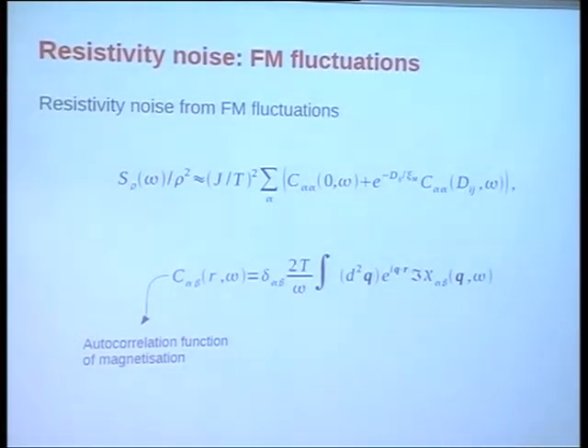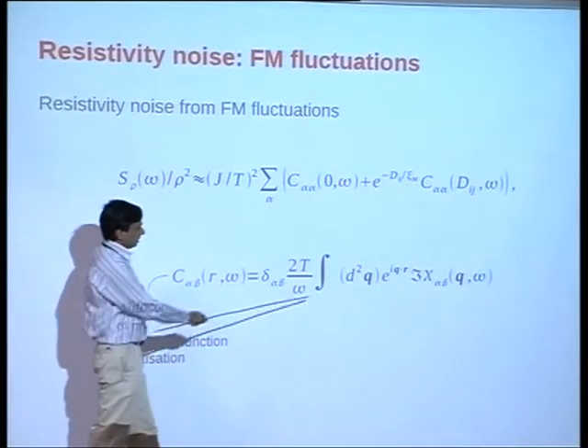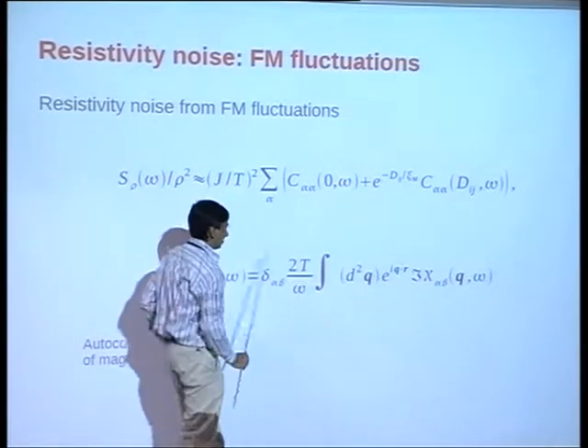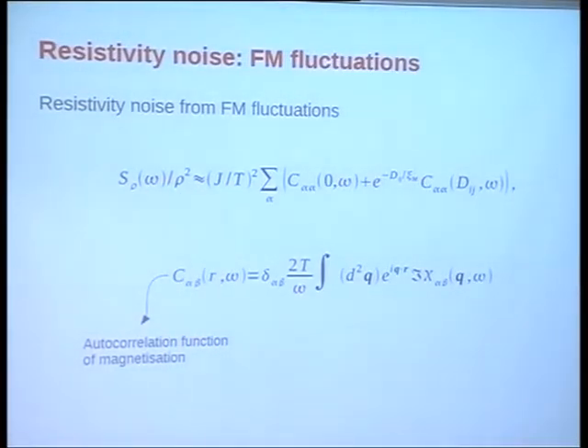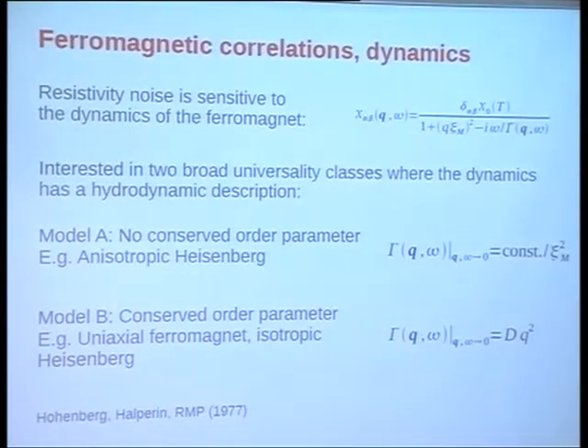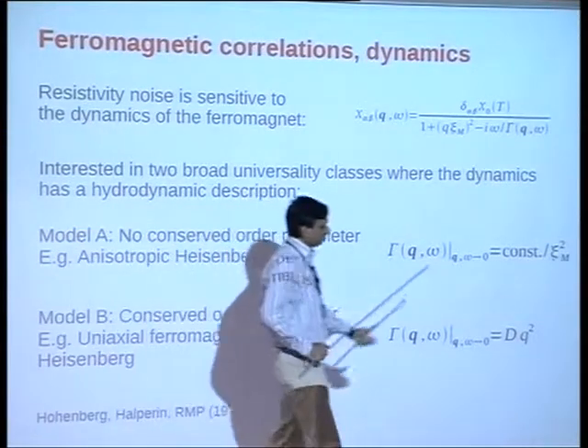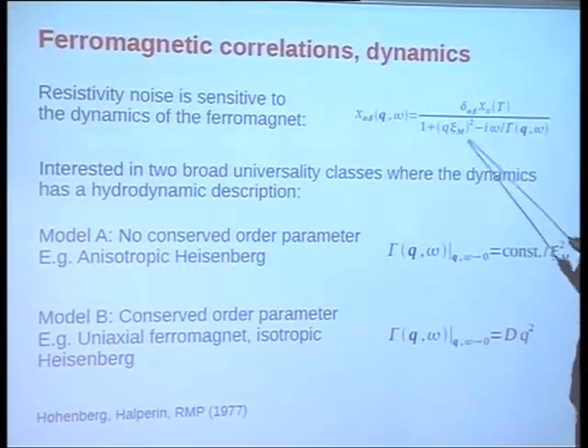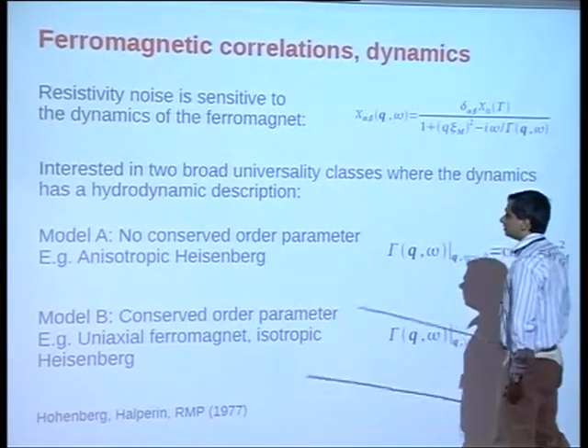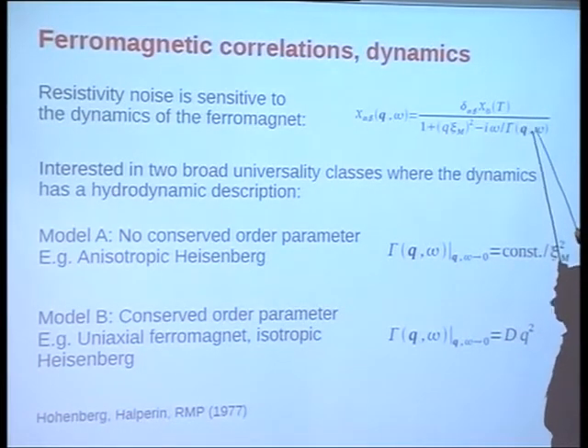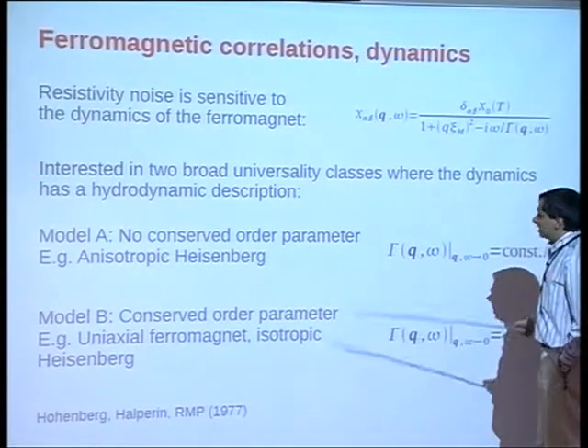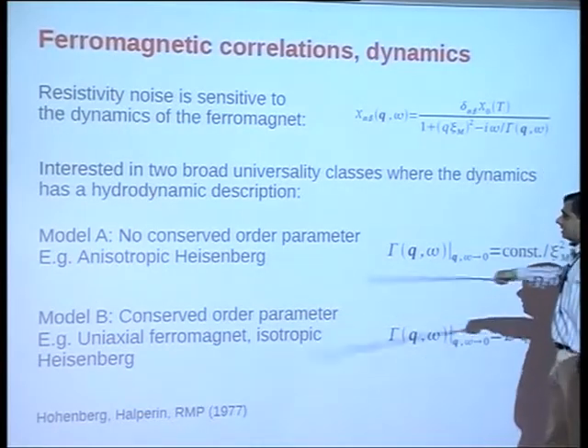I don't have time to show how we obtained an expression relating magnetization fluctuations to resistivity noise, but it's fairly simple, and it depends on the autocorrelation function of the magnetization, which of course by the fluctuation dissipation theorem is related to the imaginary part of the response function, which is the dynamical susceptibility. Now this dynamical susceptibility is quite sensitive to the mechanism of ferromagnetism. Without this dynamical part, you can get an effective Heisenberg model description for just about any of those scenarios. But this part actually cares about how the ferromagnetism came about. Had it been double exchange, it would show a completely different Γ(q, ω) than the RKKY model.